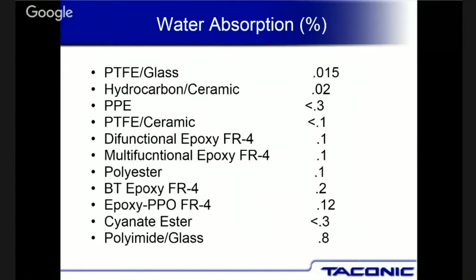And I always tell people when they're building the boards, anytime you're in doubt on what chemistries you're exposing a material to, take that board before you put it in the next process, rinse it in hot deionized water, and then rinse it in alcohol, and that'll remove the organics and inorganics so they aren't penetrating the material. Because what happens is you can expose it to chemistries, and then you go into the next process, and you can actually seal in those chemistries that you saw prior. And by the way, you're not going to see that until you heat the board up, and all of a sudden you'll see the copper blistering off, or you'll see a lot of warpage in the board, because things are happening in the materials.